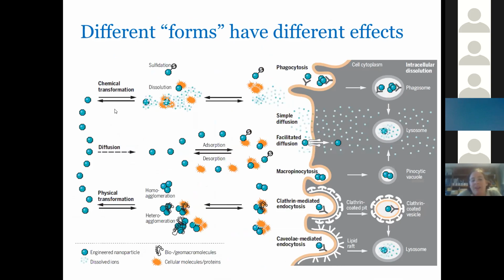So I mentioned, for example, we can have chemical transformations of our particles, we can have physical transformations, and we can have interactions with biomolecules. And all of those can be happening in parallel. So it isn't always that only one of the processes will happen. We may well end up after a few minutes with some particles that have been chemically transformed, some that have bound biomolecules, some that are a mix of chemically transformed and bound biomolecules, some that are still single particles, and some that are agglomerated. And each of these will then get taken up and interact in different ways, as shown schematically here.